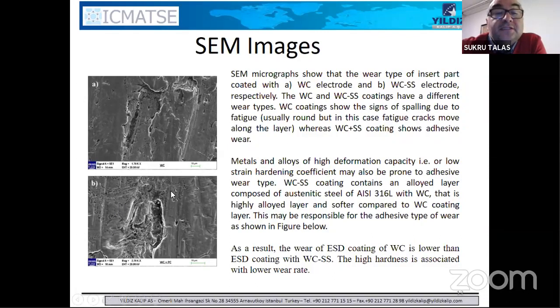This is tungsten carbide plus stainless steel. As you may see, it has uneven edges, and there's also a depth to it, which means it is adhesive wear. What happens when you're moving the sheet metal is that it takes some part from the surface and takes that small part with it. But in the first one, tungsten carbide, because the underneath is a very flat, very smooth surface, we think that this tungsten carbide layer wore because of repetitive deformation, which means fatigue deformation.